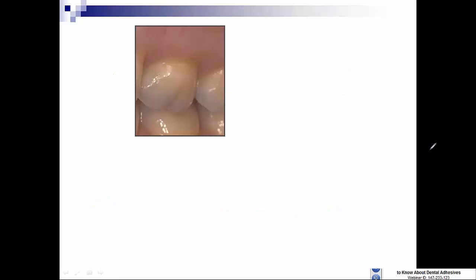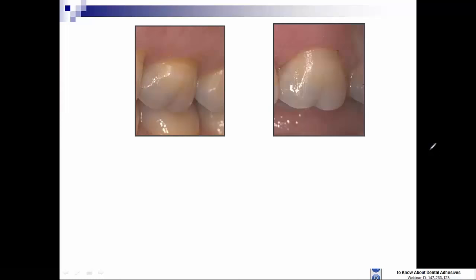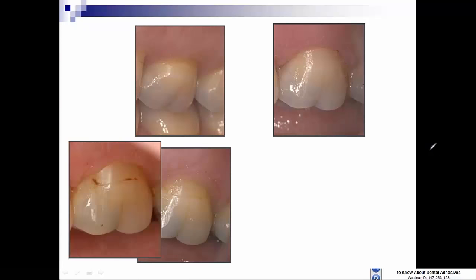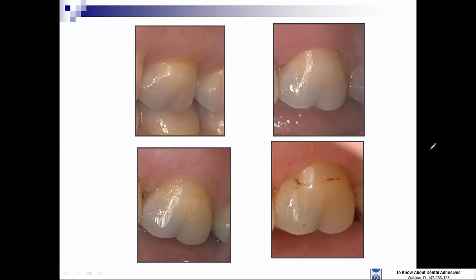effective. Now these materials are much better, so that retention rates for products like Xeno 4 and Clearfil SE Bond after 5 years exceed, without phosphoric acid etching, exceed 90%. But another problem of all of these self-etching systems is marginal stain and marginal gap formation. While the modern self-etching adhesive systems rival the etch and rinse systems in their bond to dentin, they are totally inferior in their bonding to enamel. So in clinical situations where enamel is present, these self-etching adhesive systems lack sealing ability and have a propensity, as shown in this series of slides, for stain around the enamel margin.